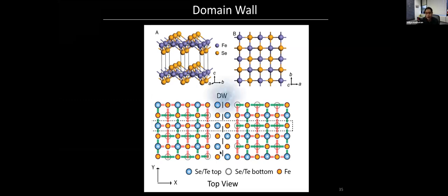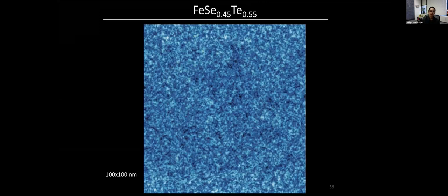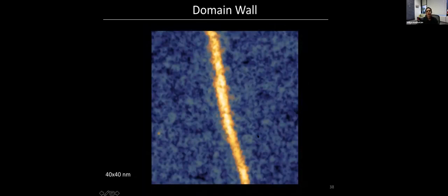realize propagating Majorana fermions. So, the samples normally look like this. You don't see any signs of domain walls, but if you search around, you can also see regions like this, where you have these long lines. And not all of these lines are domain walls, but if you search around long enough, then you can find the right kind of domain wall that we're looking for.